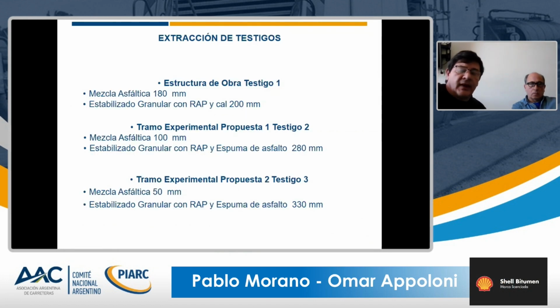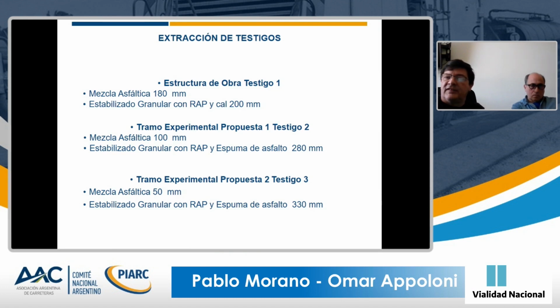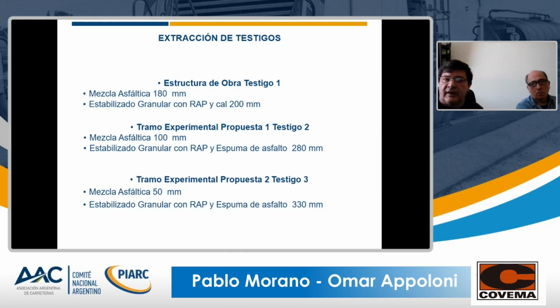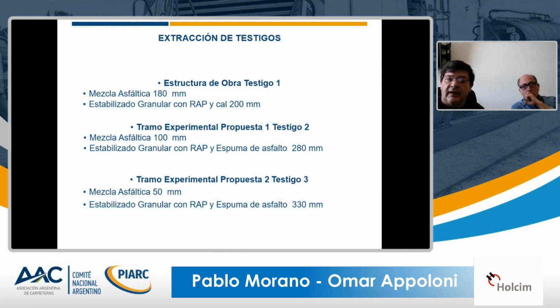Here on this page, we can see that the original work consisted of granular stabilization plus 180 millimeters of asphalt mix. In the experimental stretch, which was 100 meters, we had granular stabilization with RAP and foamed asphalt at 280 millimeters and an asphalt mix that was 100 millimeters.